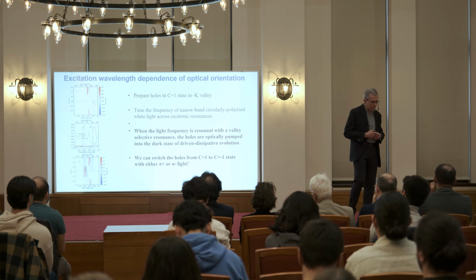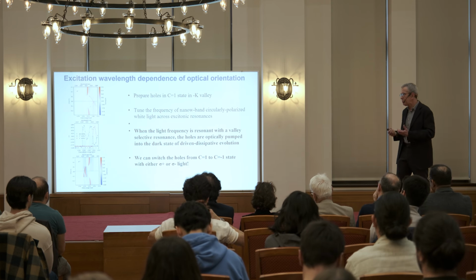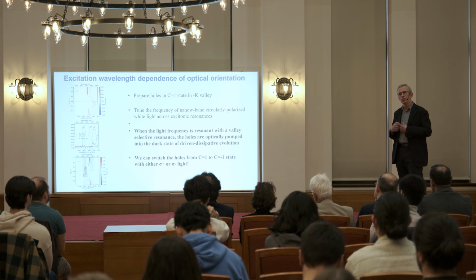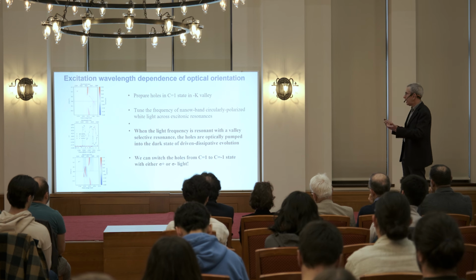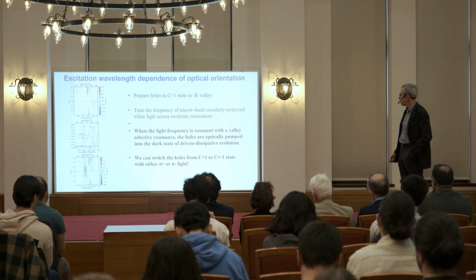And I want to point out that even though I told you what we can do with sigma plus excitation, if we use sigma minus light with another resonance, another frequency, we can also do the same switch. So this is not an angular momentum transfer, but we're basically using polarization or spin selective excitations to push the system in the direction that we want to go.